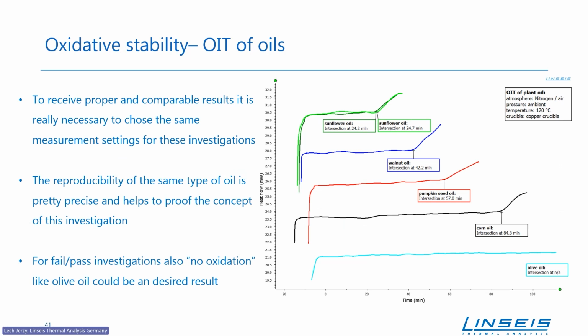Another topic is also, yeah, this is what we have done with oils. And as I mentioned, in this case, it can be simple test for quality control. If there is no oxidation, it can be expected as positive result. Atmosphere of this measurement is nitrogen switched to air, and we lead this measurement up to 120 in copper crucibles. We can say there is no oxidation for olive oil, but we can see visible oxidation for sunflower oil in much lower rate.